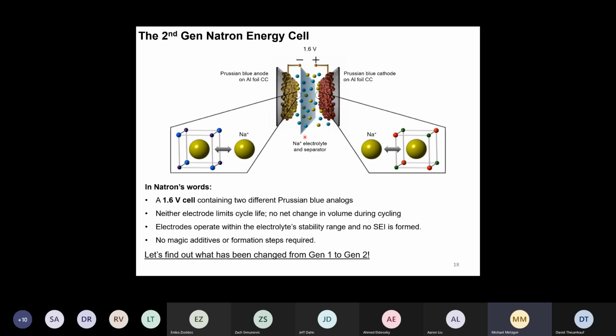So here they say, maybe let's read their words down here. So it's a 1.6 volt cell now compared to the 1 volt cell that you saw before, with 2 different Prussian blue analogs. They say neither of the electrodes limits the cycle life, and there is no net change in volume during cycling. The electrodes operate within the stability range of the electrolyte. And the really cool thing is, because of that, you don't form a passivating layer on the electrodes. So no SEI, no solid electrolyte interphase is formed in their technology.